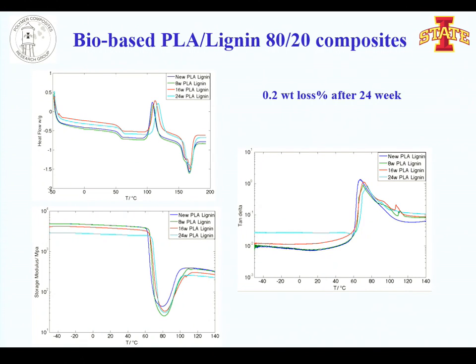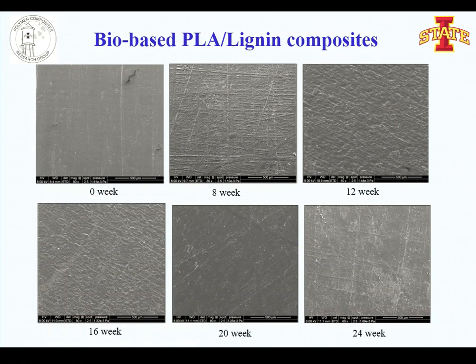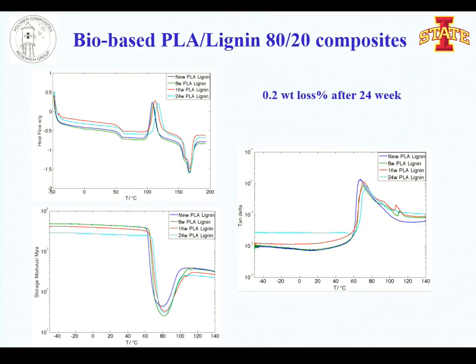We have one example here. I'm still talking about PLA. We mixed the PLA with 20% lignin, and we found that the glass transition temperature is almost the same, does not change, but the crystallization is shifted systematically to higher temperature, and the melting is also shifted a little bit to higher temperature. This is again due to the degradation taking place on the amorphous part and not on the crystalline part. There is a very slight change in the elastic modulus and nothing changes in the glass relaxation process of the material. And as you can see, we haven't seen any degradation. After 24 weeks, it is just 0.2% loss in weight.